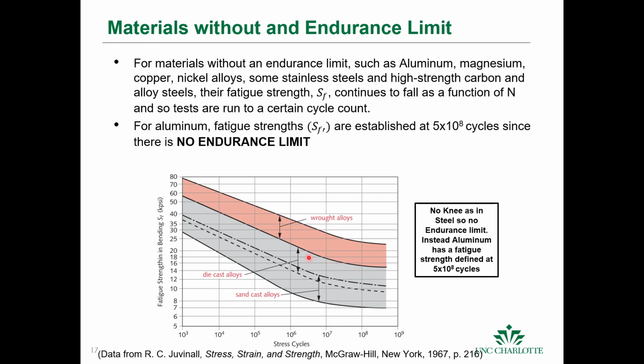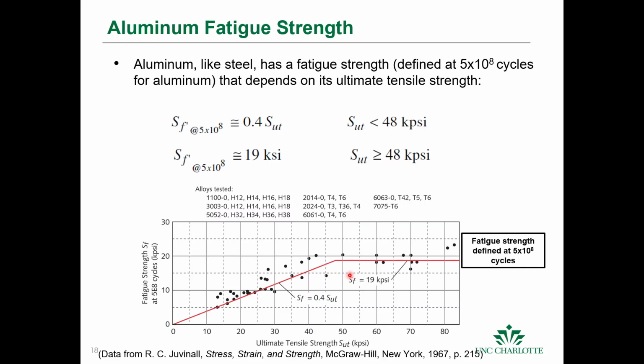The material manufacturing process also has a dramatic impact on the fatigue strength of a material. This shows the fatigue strength here of a wrought alloy. I believe this is for aluminum. This is for die cast, and this is for sand cast. And obviously sand cast has a rough surface, so it gives plenty of opportunities for cracks to initiate and propagate into catastrophic failure. So for aluminum, like steel, we can still say that there's a fatigue strength, but we define it at a certain number of cycles. We don't give it an endurance limit.